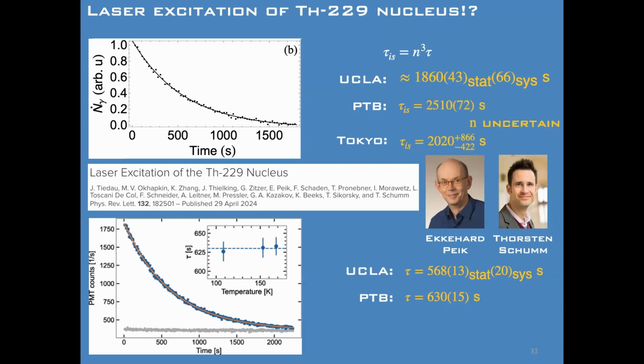And we may know that actually it's kind of a very weird month for thorium. At the same time, there was a result from Tokyo, Yamaguchi, who works with Katori, did a trapped ion measurement. They didn't excite the nucleus. They basically took the experiment I showed you earlier from Peter Thirolf and put an ion trap at the end instead of an MCP. You can take spectroscopy of the thorium, and when the excited state decays, the hyperfine changes. And so you can get a rough estimate of the lifetime. It's a pretty big error bar, but it's all in the same time.